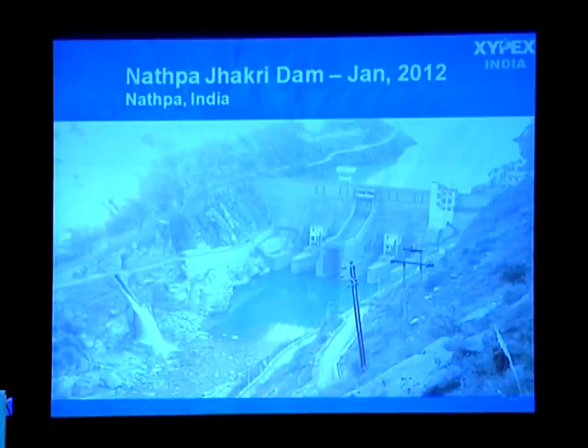The second project that we did was in the northern part of the country, which is Nathpa Jhakri in Himachal. The unique situation of this project was that there was a very, very high silt content in the water. And because of this high silt content, there was significant erosion of the surface of the piers of the spillway basin. On average, every year we were losing around 5 to 15 mm of surface.